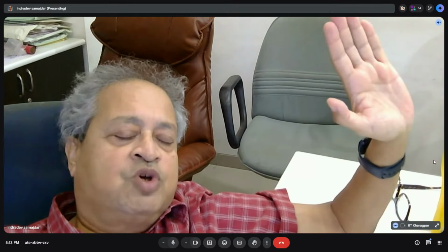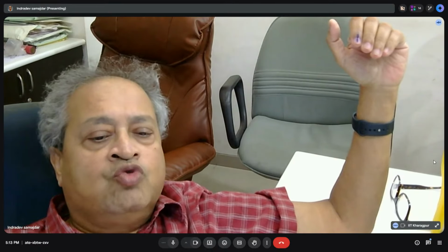Yes, sir. Sir, I have 2 more questions if you would like to take. Please do. Sir, you talked about the micro diffraction. What is the typical beam diameter in that micro diffraction? What we can achieve in our system is 50 micron, I'm sorry, 50 micron. I don't think anything lower than that is doable, except with synchrotron intensity. And there you can go to 5 micron.